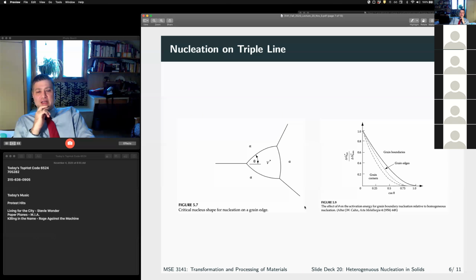So triple lines are even higher energy, right? So they're even much more potent nucleation sites. And grain corners are even more. So this ratio, we get a big boost by potentially considering nucleation at triple points, triple lines, okay? So if we look at this ratio,